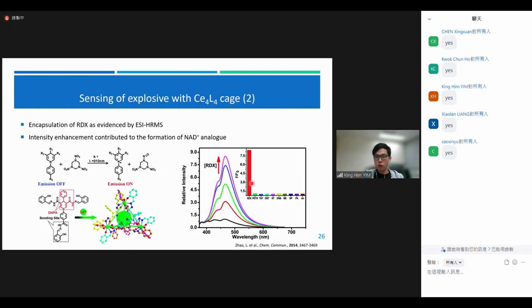And here also shows the high selectivity of this cage, because they try to use, for example, TNT, DNT, and the other explosives, but only RDX shows a very high selectivity towards this cage. The emission enhancement is almost 7.5 times, which is higher than the other explosives.